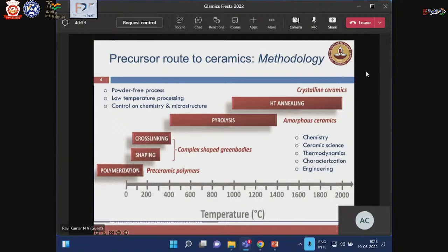It's a powder-free process, so we don't do any sintering of materials. Because we start with individual monomer units, we start with precursors, there is no question of handling of powder, so it's a completely powder-free process. As I already emphasized, it's a low-temperature processing, and then we have excellent control on chemistry and microstructure. It's a highly interdisciplinary field where we start with chemistry and go all the way to the level of an engineering component which can be used in the industry. So it's highly interdisciplinary in nature.